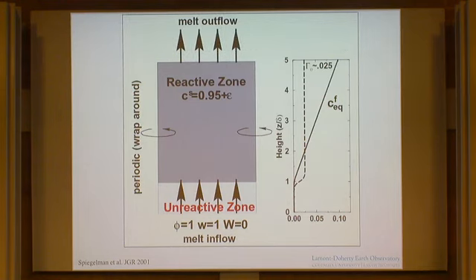But first, Marc Spiegelman worked with us for many years, and we tried to do a very simple model of this dissolution instability, incorporating viscous compaction, incorporating this two-phase flow idealization where the upward flow of the buoyant melt is coupled to downward flow of the dense residue. Okay, with the question, as these channels begin to form, will they be crushed by compaction, so to speak? What will happen?